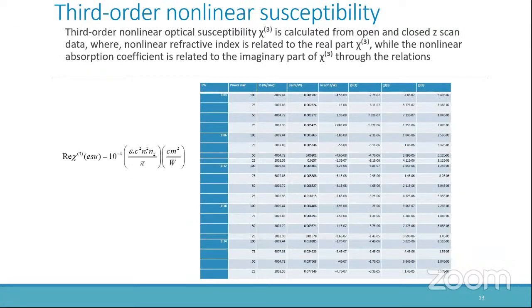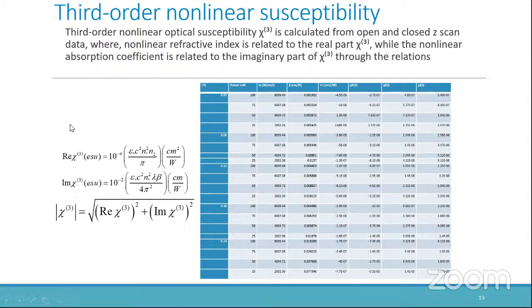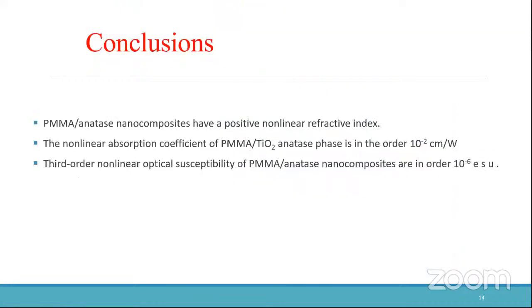So third order nonlinear optical susceptibility is calculated from open and closed Z-scan data, where nonlinear refractive index is related to the real part, while the nonlinear absorption coefficient is related to the imaginary part of the chi3 through the relations. So these relations are used to calculate the third order nonlinear susceptibility, and in these 2 columns we have given the data which present the third order nonlinear susceptibility.